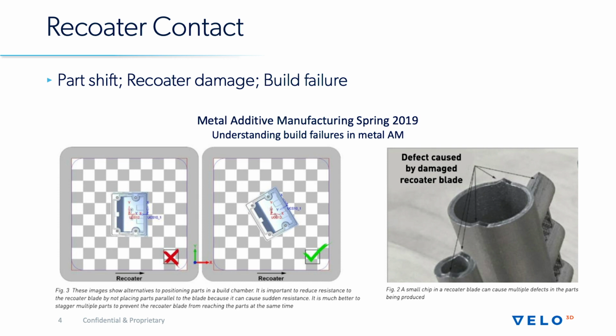Another possible thing that can happen is that the part is protruding out of the powder bed and will actually damage the recoater, which can then cause defects within the powder bed itself, which then on subsequent layers get lazed onto the parts themselves. An example of this is shown in the bottom right-hand corner here, a very classical powder bed streak, which then imprints itself onto the part. And then finally, the ultimate form of recoater failure is just the entire build failing because of a catastrophic collision between the recoater and the parts.